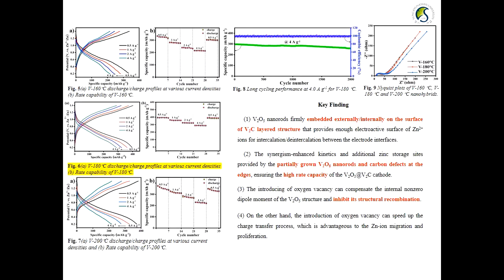The introduction of oxygen vacancy can compensate the internal non-zero dipole moment of the V2O5 structure and inhibit its structural recombination. On the other hand, the introduction of oxygen vacancy can speed up the charge transfer process, which is advantageous in the Zn migration and diffusion.